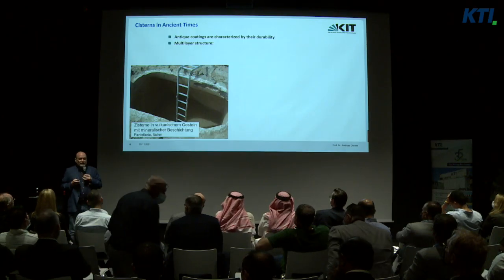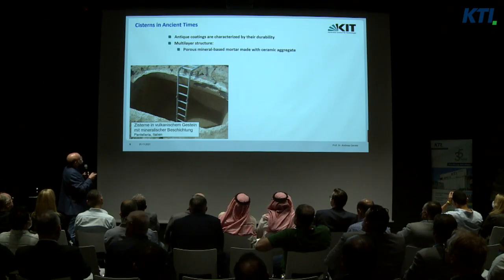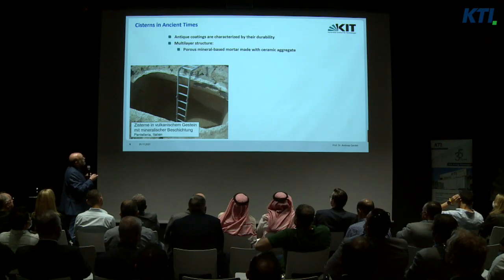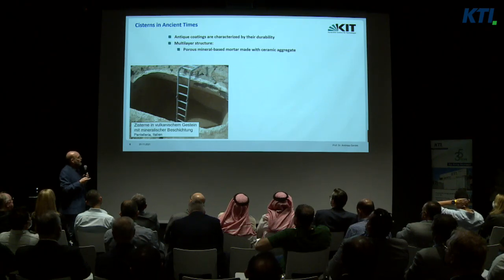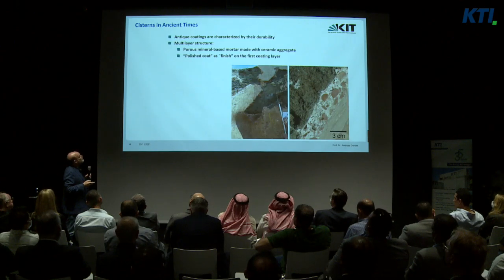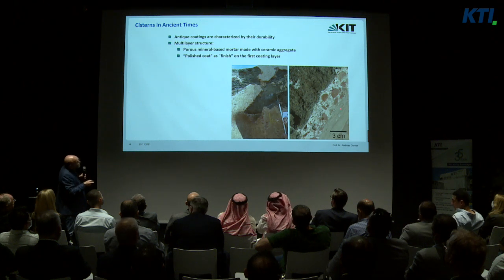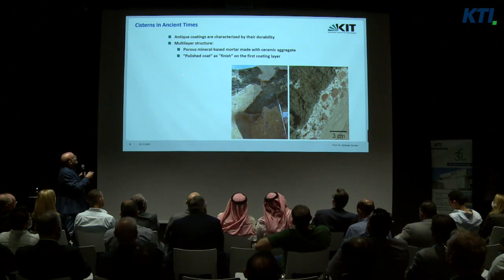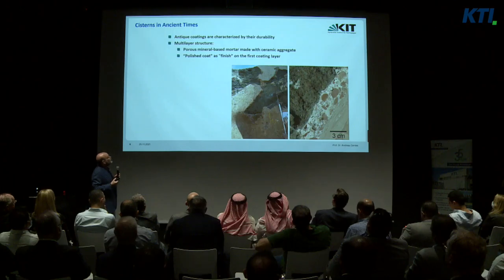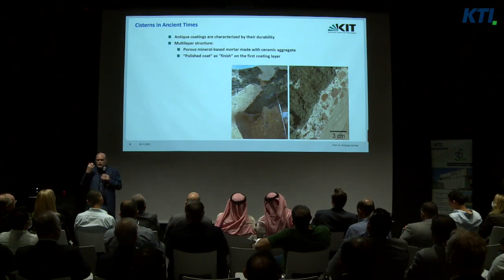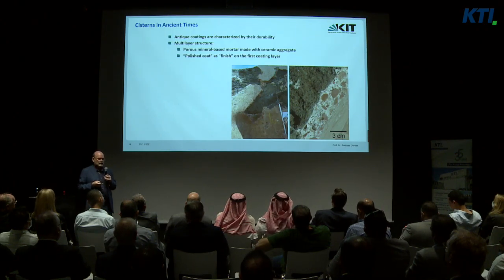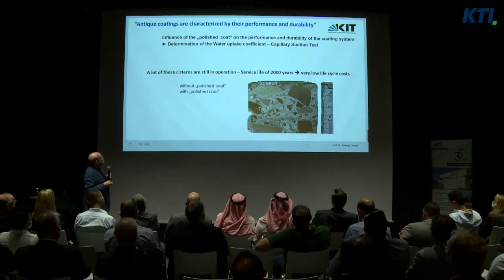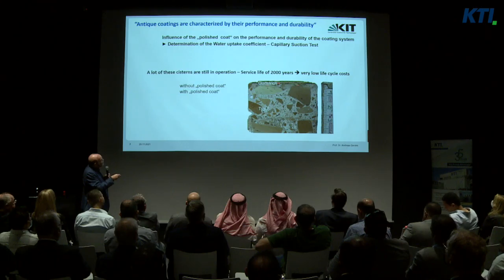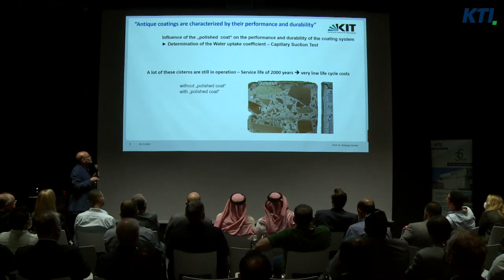We have a multi-layer structure. A first layer with a porous mineral-based mortar made with ceramic aggregates. And then on the first layer, a very thin layer is put on it. You can see it here. And this is like a polish coat as finished on this first porous coating layer. And that leads, you can see it. This is a core from this material, the porous material, and the polished finish.